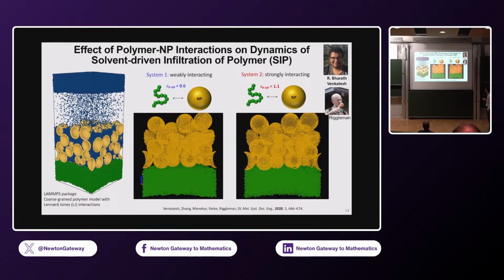So I collaborated with Rob Riggleman. I have a very talented student who did both experiments and computational studies. So we made essentially a computational model of what our system looks like. These are the nanoparticle packings. That's the polymer. Solvent is filled, but I've removed those, so we can see what happens to the polymer as we change the interaction strengths between the nanoparticle and the polymer. Okay, so this is stronger interactions between the two species. And we can run these simulations.